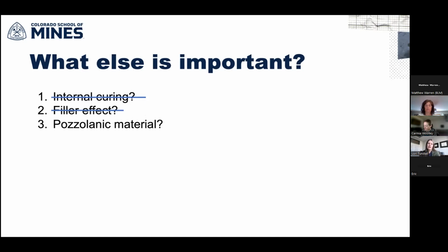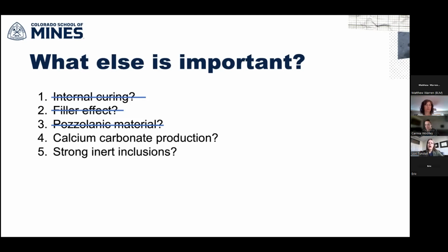Another thing that has been speculated is, does the biochar act as a pozzolanic material? Depending on the type of biochar you use, you can get varying amounts of carbon and ash. Fly ash, which you might be familiar with, is very beneficial in concrete because it has a pozzolanic effect, which basically means that it produces more calcium silicate hydrate, the glue that ties everything together. However, we've also eliminated that as a potential mechanism. So these are the three predominant mechanisms proposed in the literature for what's happening in the biochar mixes. We've ruled all three of those out in this really thorough investigative program. So now we're exploring two other potential hypotheses.